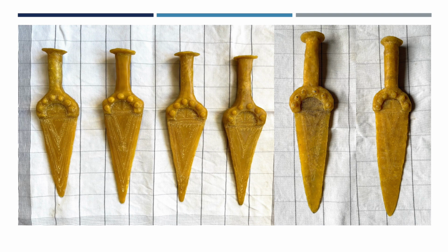My first incisions, the first four daggers, I carved the lines far too deeply. However, when I was discussing with the two metallurgists who made the other replica dagger, they taught me some things about wax, and one of these facts was that with lost wax casting, if you're creating very delicate decorations, you don't need to press too hard as you make them. A very fine incision will be just as visible in the final product as very deep incisions.